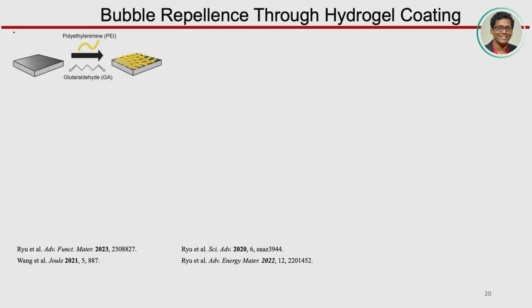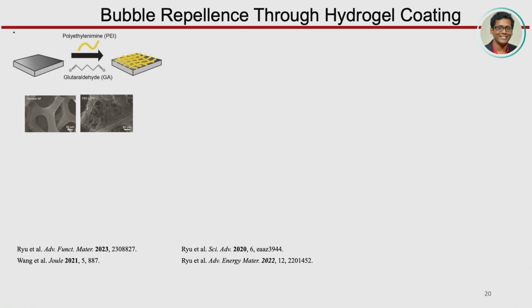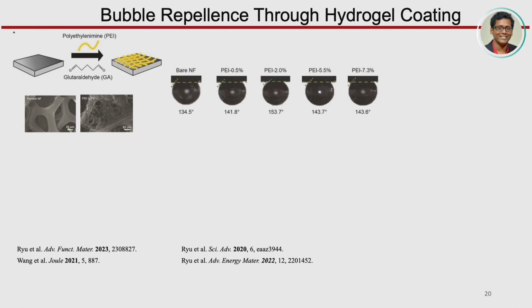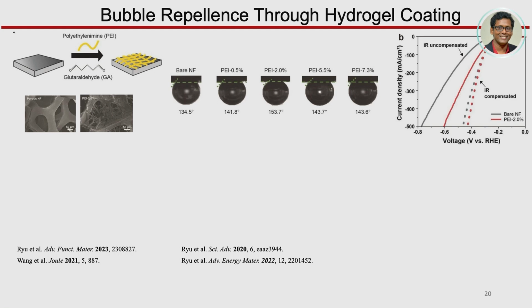the electrode surface. As you can see here, they took polyethylenimine and glutaraldehyde, which undergo imine formation, but that chemistry is still labile, right? If you put it in acidic conditions or even in water for a long time, we know the imine bond will not be stable for a long time. But for the proof of concept, you can see that once they deposit it on this nickel foam, it really modulates the bubble repellency, and their LSV shows significant improvement in terms of HER, right? And when you do the resistance corrections, then the performance is similar. So it's not a catalytic performance, it's just the bubble dynamics, how you play.